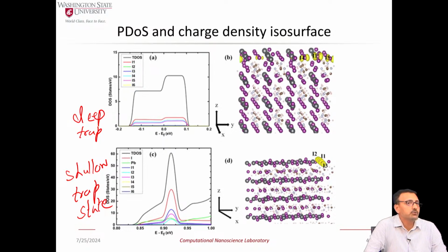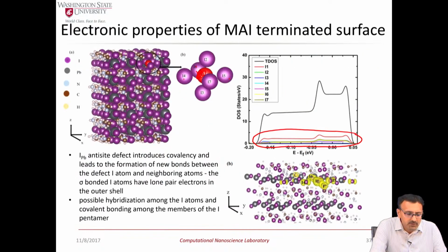But going back to the question we had earlier, this required quite a bit of energy minimization first, before we do the density of states calculation. The energy minimization is pretty intensive, and at first we used a slab size where we did see some spurious effect of defect interaction, but then we introduced more atoms and increased the XY dimension of that slab. I don't remember the size off the top of my head. Let me go back to the paper. So your question is, what is the size of the system here, right? Give me a moment.